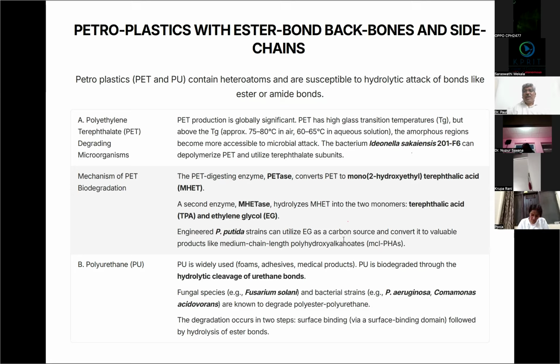PET has a high glass transition temperature, but above the glass transition temperature, it can change from the crystalline or semi-crystalline state to an amorphous region, which becomes more accessible to microbial attack. In 2016, a bacterium called Ideonella sakaiensis was isolated, which can depolymerize PET and use the terephthalate subunits for its growth.